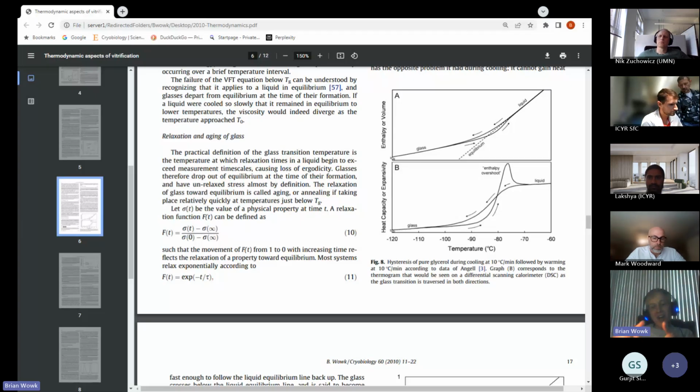If you stop cooling right at the laboratory measured glass transition, those parameters will continue relaxing with a time constant of about 100 seconds. And this is intrinsically related to our human time scale and the patience of an investigator.